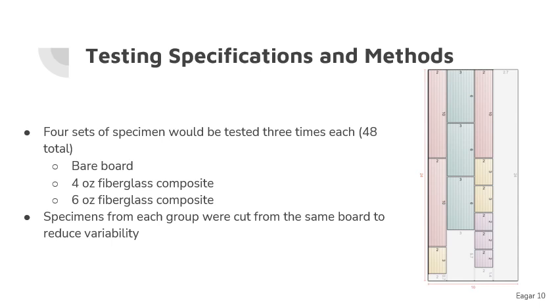So the bare board, the 4-ounce fiberglass composite, and the 6-ounce fiberglass composite. We were also going to test a carbon fiber composite on the bare board, but we did not end up having the time available to us to manufacture those boards. So specimens from each group were cut from the same board to reduce variability, and as you can see on the right, we had a dimensional analysis to determine how we would cut those specimens out of the board.